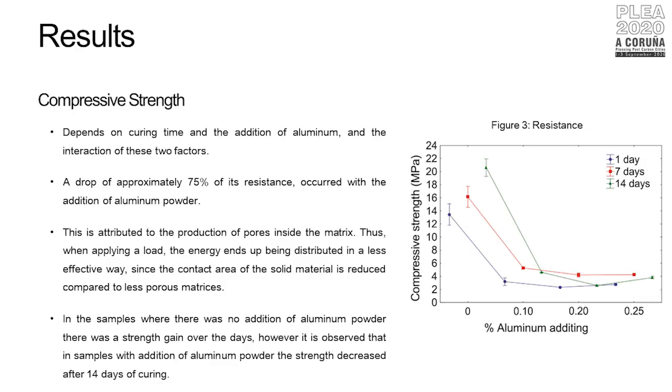In the compressive strength graphic, it is possible to identify a drop of approximately 75% of its resistance that occurred with the addition of aluminum powder. This is attributed to the production of pores inside the matrix. Thus, when applying a load, the energy ends up being distributed in a less effective way, since the contact area of the solid material is reduced compared to less porous matrices.